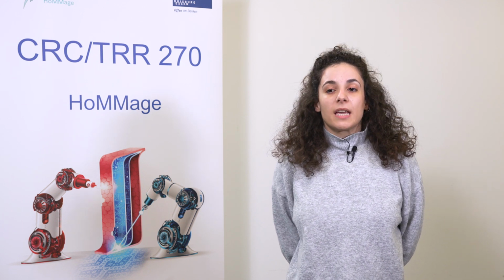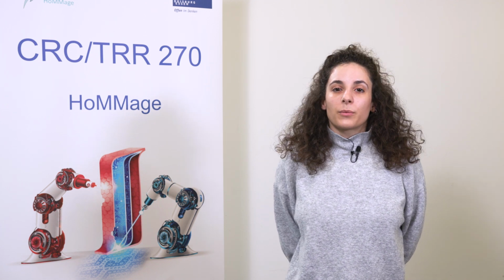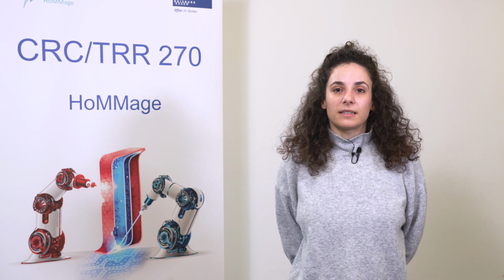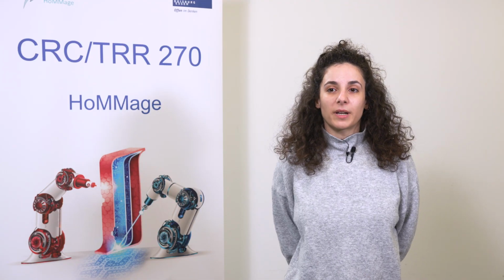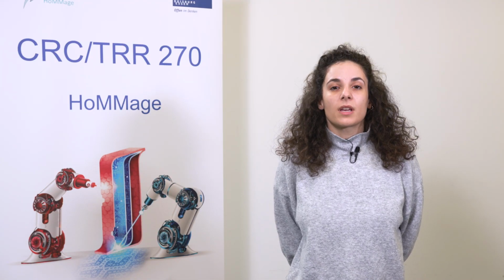Samarium cobalt is one of the most known permanent magnetic materials. We grow this material in the form of thin film in order to understand the hysteresis mechanism. Going really in nanoscale, we have the opportunity to study the material and understand what is happening at the atomic level. Molecular beam epitaxy gives epitaxial thin films, and this also gives us the opportunity to have atomic layer by atomic layer and study the interactions. This will give us then the understanding for hysteresis mechanism and apply for bulk magnetic materials.